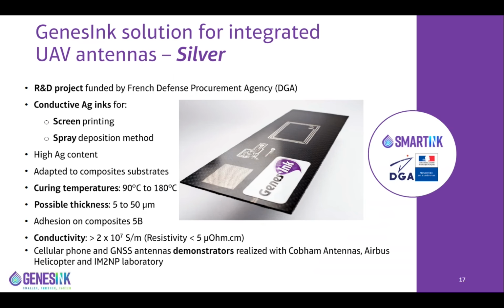We developed conductive high silver loaded inks suitable for screen printed and spray deposition methods and adapted to various composite substrates. We were able to tune the thickness of the conductive layer of the integrated antennas using one or several passes to reach the best performance in terms of conductivity, adhesion, and radio frequency, even for 5G, with excellent reliability in different standard environmental conditions. For example, they passed climatic, mechanic, and vibration tests.